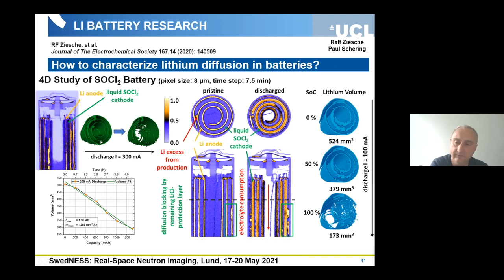So in case of time-dependent tomography, we can investigate the process in 3D. We can see in 3D the lithium consumption in the battery. So all the changes which are related to the electrochemical process can be visualized in 3D. Here, the time resolution was about 7.5 minutes per tomography with a pixel size of 8 micrometers. This experiment was performed at ILL with really very high intensity, which is available there.